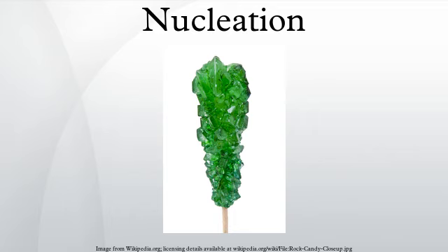Heterogeneous nucleation. Heterogeneous nucleation, nucleation with the nucleus at a surface, is much more common than homogeneous nucleation. Heterogeneous nucleation is typically much faster than homogeneous nucleation because the nucleation barrier ΔG* is much lower at a surface. This is because the nucleation barrier comes from the positive term in the free energy ΔG, which is the surface term. For homogeneous nucleation the nucleus is approximated by a sphere and so has a free energy equal to the surface area of a sphere, 4πR², times the surface tension γ.